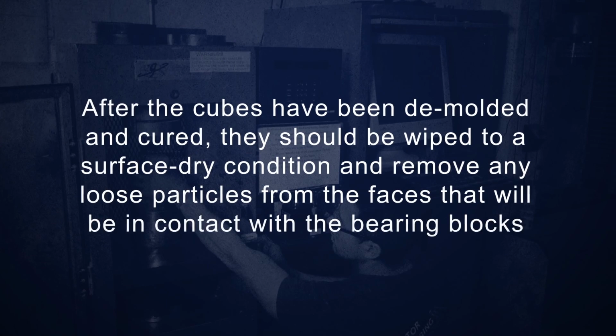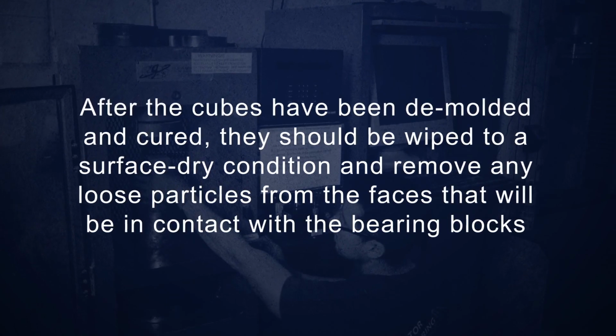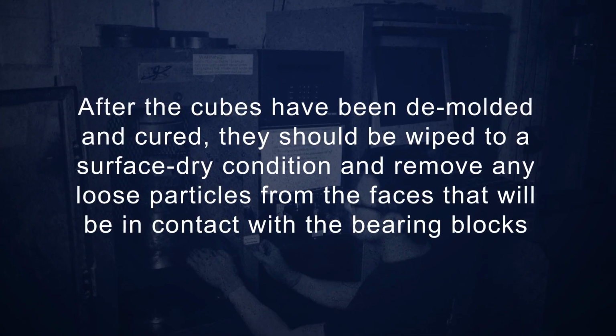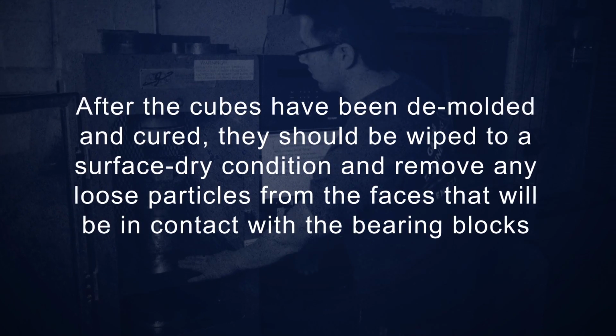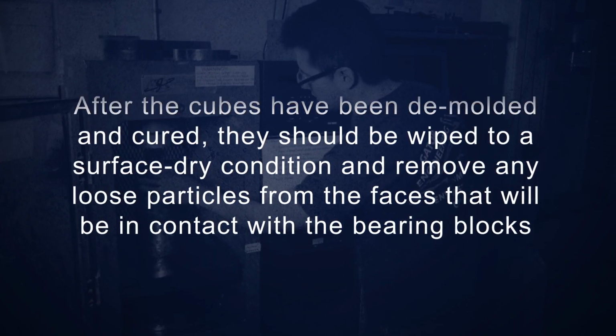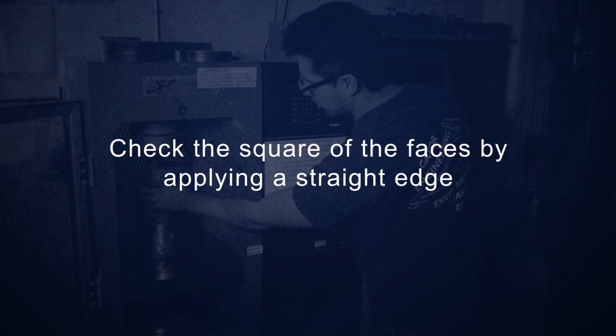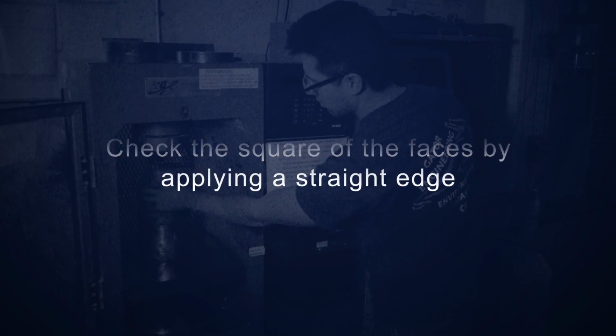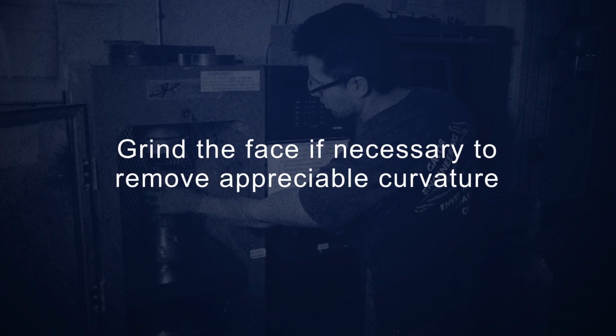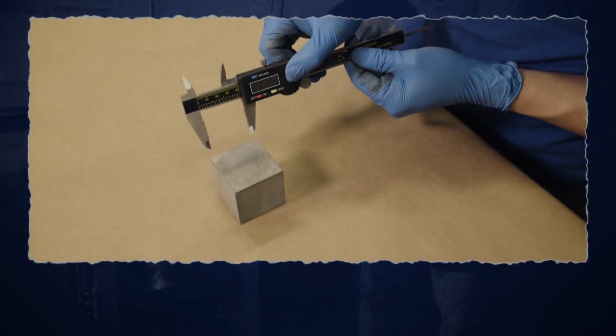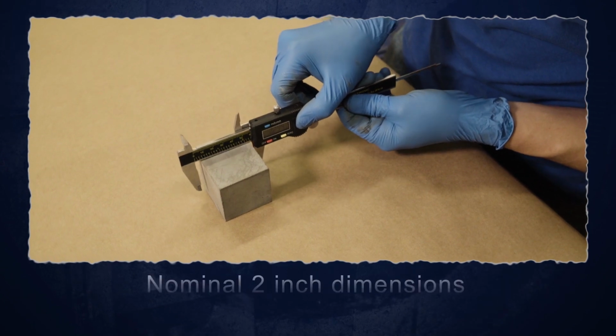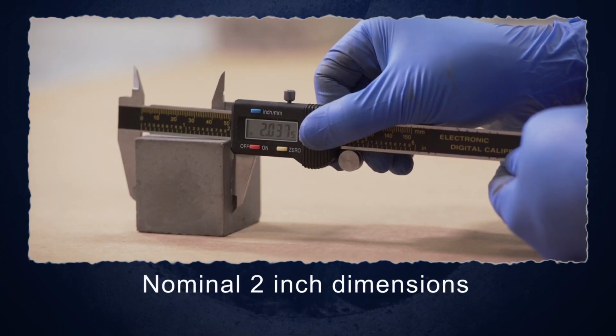After the cubes have been demolded and cured, they should be wiped to a surface dry condition and any loose particles removed from the faces that will be in contact with the bearing blocks. Check the square of the faces by applying a straight edge. Grind the face if necessary to remove appreciable curvature. Measure cubes to ensure that the actual dimensions match the nominal 2-inch dimensions.